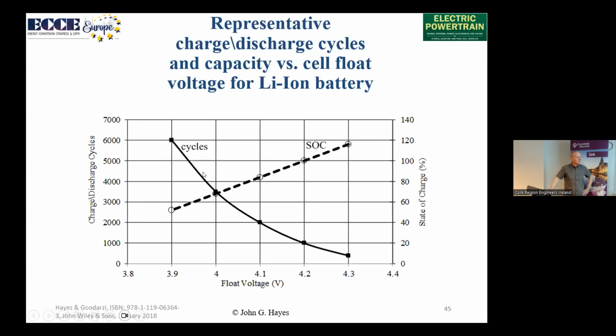So now I talked about the challenge we have with supercharging the battery. So we'll just start here, just an interesting slide that I formed based on something I've seen years ago. Here, what we call the float voltage, just the maximum voltage we're going to put across the cell. Over here is the number of charge-discharge cycles that the cell can withstand before it degrades by about 20%. And over here is the stated charge. We typically like to standardize on 1,000 charge-discharge cycles. And that can happen with a max voltage, a float voltage, of about 4.2 volts. And that will be 100% state of charge. I can move more lithium into the anode, push up the stated charge to almost 120%, increase the voltage to about 4.3 volts, but the number of cycles I can withstand is about 300 cycles. I've significantly damaged the lifetime of the pack.